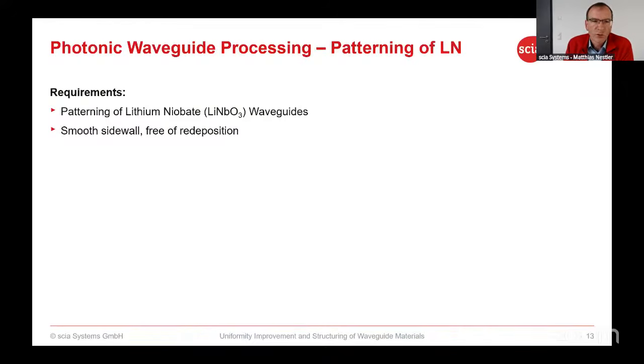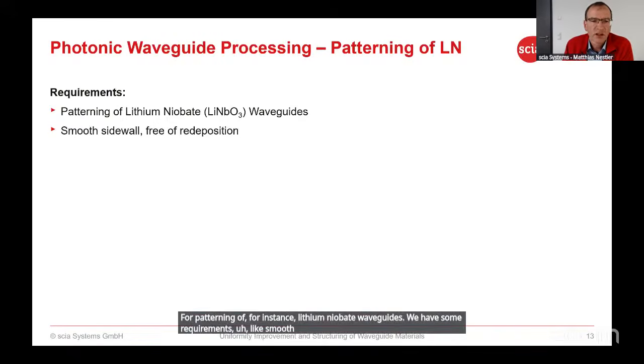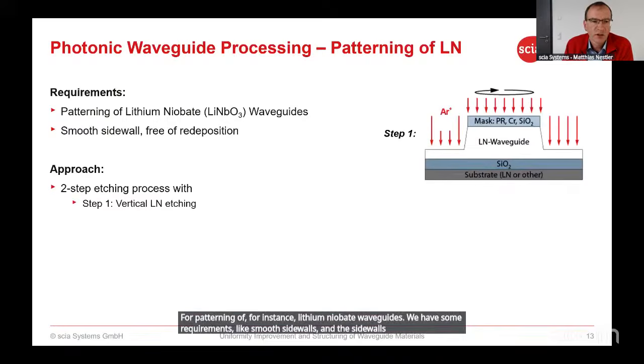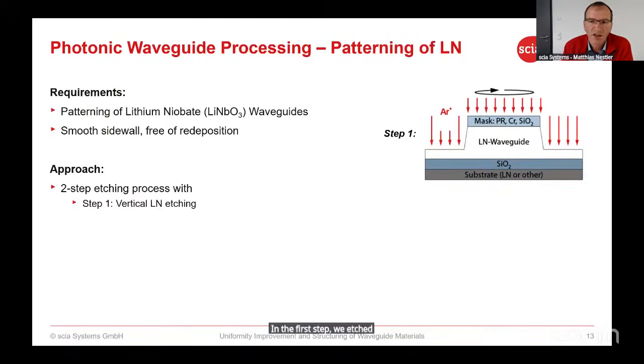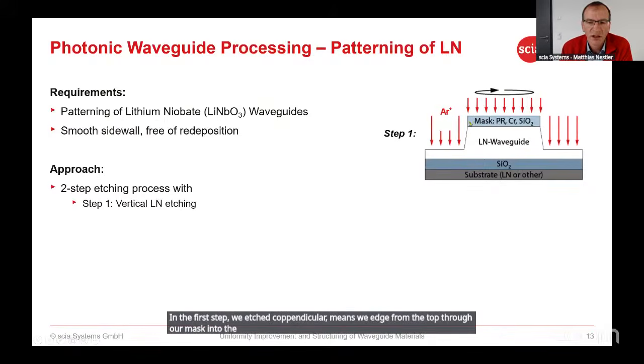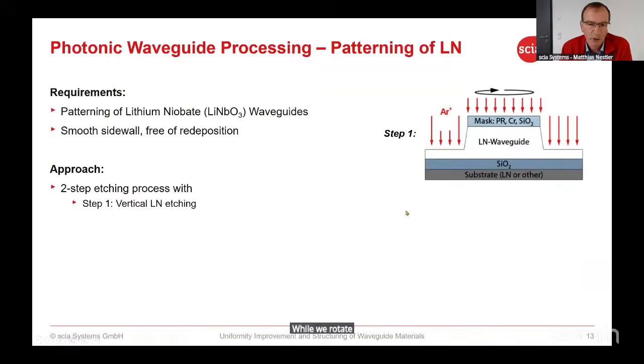For patterning of, for instance, lithium niobate waveguides, we have some requirements like smooth sidewalls, and the sidewalls should be free of redeposition. And therefore, we have a two-step approach. In the first step, we etch perpendicular, meaning we etch from the top through our mask into the lithium niobate and create there the waveguide while we rotate the substrate, the wafer.